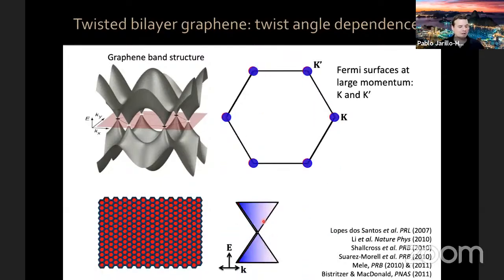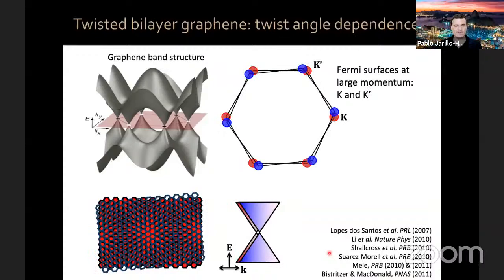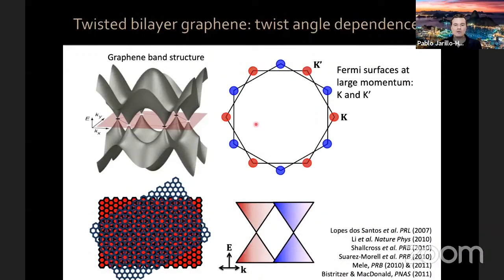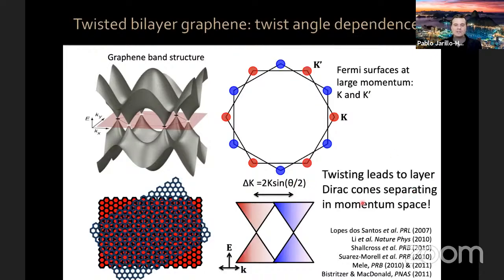If we now put another sheet of graphene on top, if the two sheets are perfectly aligned, then you get an aligned reciprocal space and real space zone. If you, however, now rotate by some angle, the reciprocal spaces rotate also by the same angle, and the Dirac cones of graphene sheet one and graphene sheet two get separated in momentum space, by a quantity which is proportional to the sine of half the angle. So twisting leads to layered Dirac cones separating in momentum space.